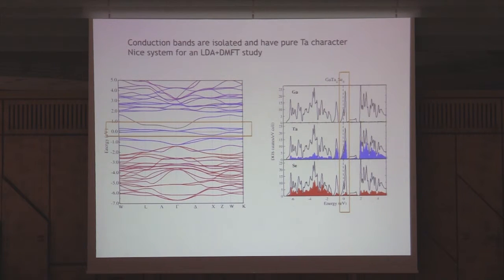So with this, we said, well, let's try to do theory as best we can. And as I said, this system is so nice that also from the band structure calculation point of view, it's very nice to do a LDA plus DMFT calculation. Why? Because this is the LDA bands. And as you see, the 3 T2G bands that I mentioned as the important ones with the one remaining electron per tetrahedron are there and are well separated from the rest of the valence band and from the rest of the upper empty bands.